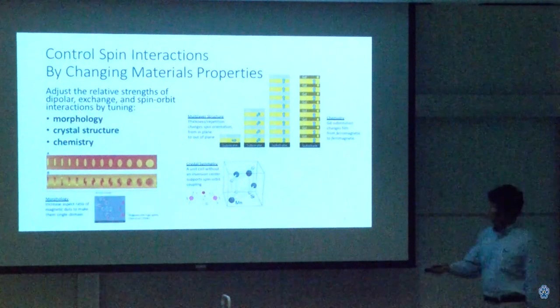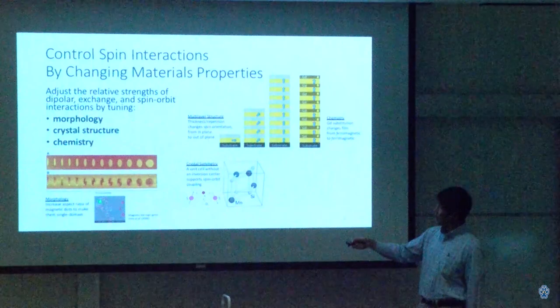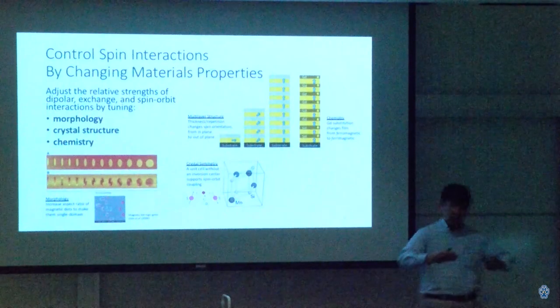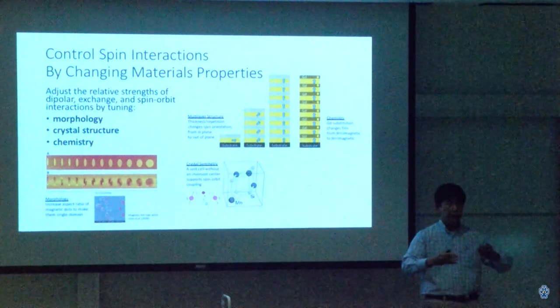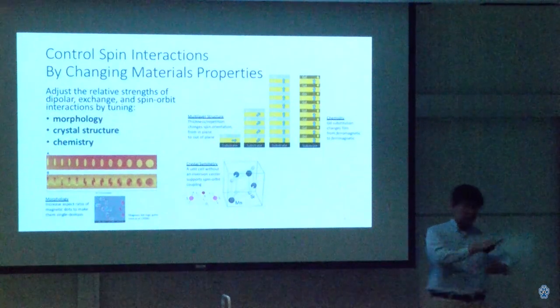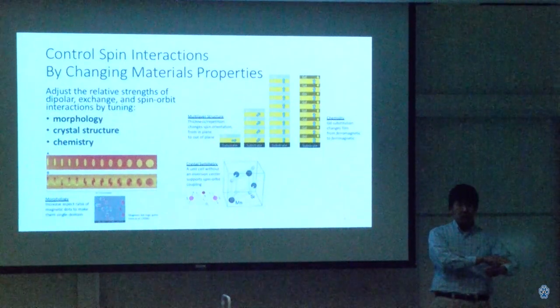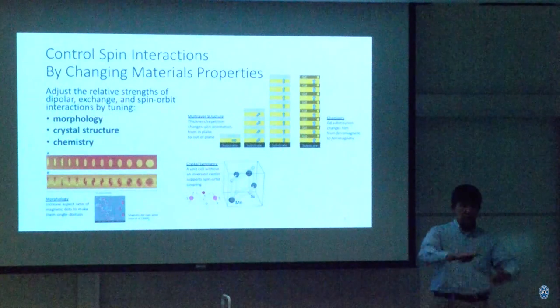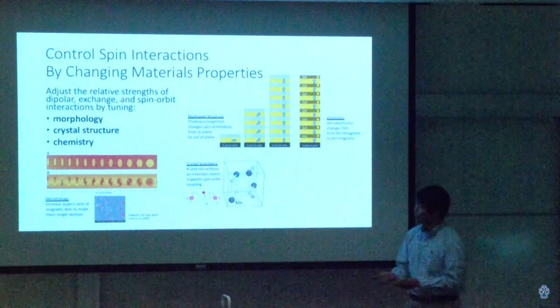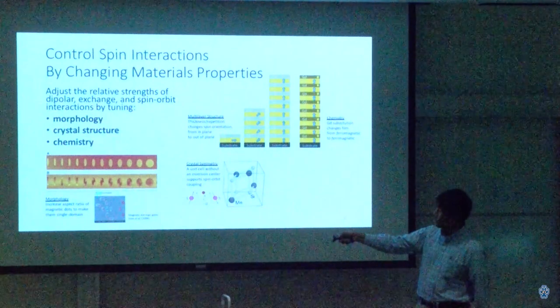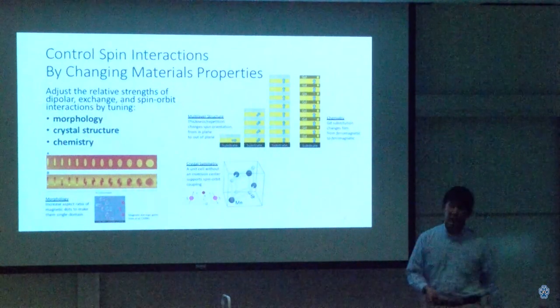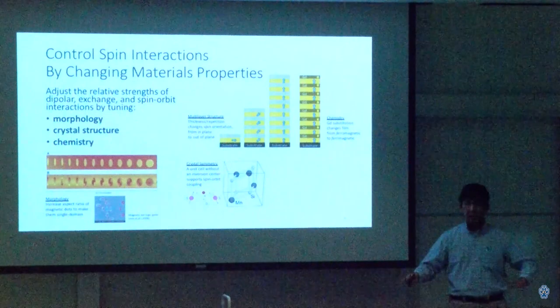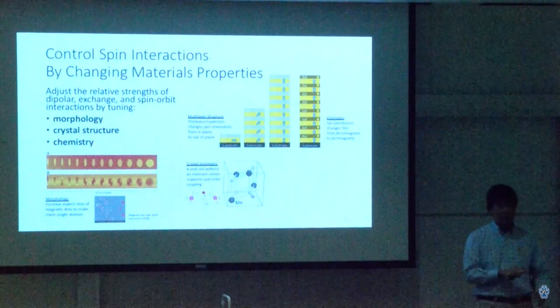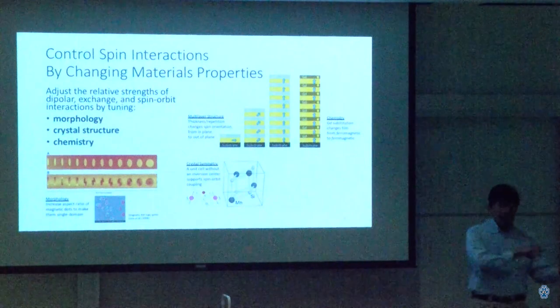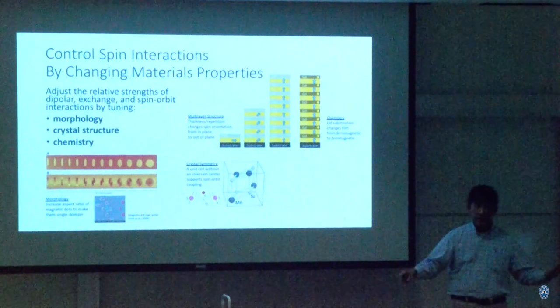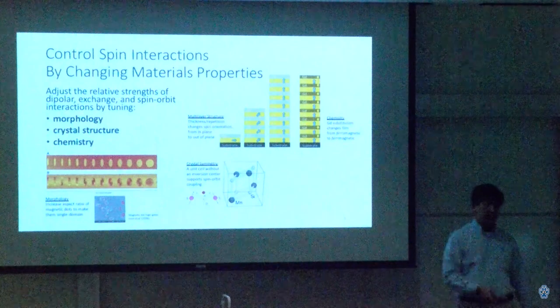Well, let's say you make these candy bar-like magnetic dots and put them next to each other. That means they can interact via their magnetic dipole fields. If you change the magnetic dipole moment on one of the dots, you can potentially get the other to move around. The researchers here attempted to create a prototype magnetic logic gate by having a series of these magnetic dots located next to each other. And they wanted to see whether or not changing one dot, interacting via the dipole field, can cause the other dot on the other end to flip. The answer was yes.